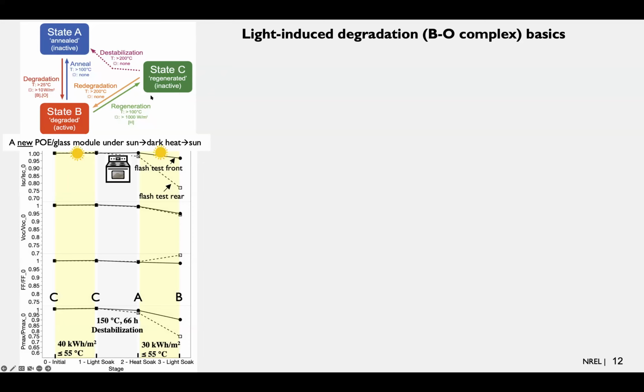So what we did to understand how the cells and modules we were working with behaved, we checked them out and ran them through this little sequence that I'm showing here. We took one of these new modules, nothing to do with CAS now, another replica of modules we had that had polyolefin encapsulant and glass on the rear, and we put it under the sun first, then in dark heat, and then under sun again, and that's graphically shown here. So first, the module we assume is shipped in the C state, and then we expose it to a light soak outside for a couple days, almost a week, and we see that there's no change in power.